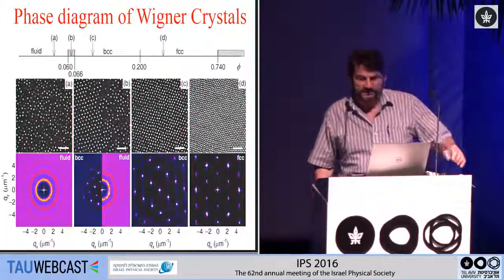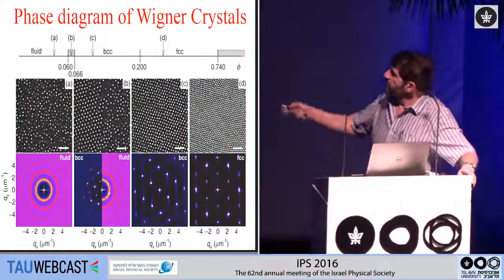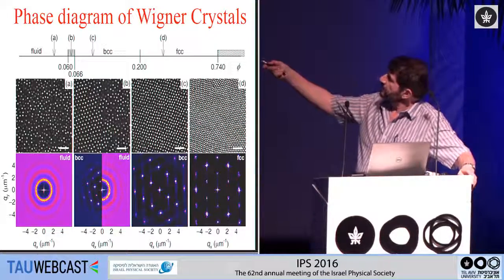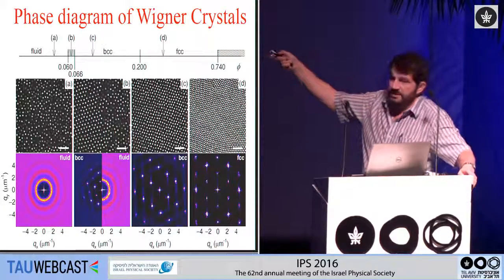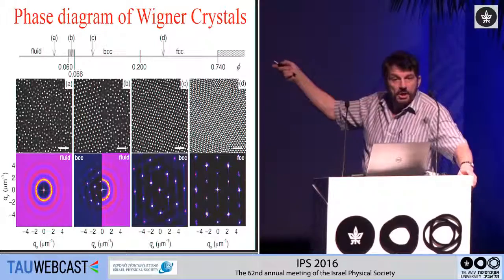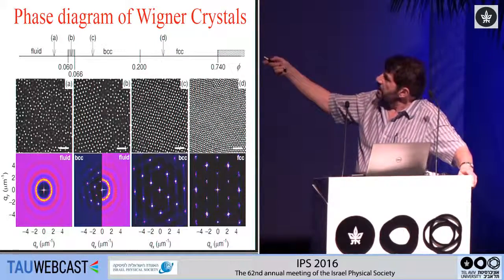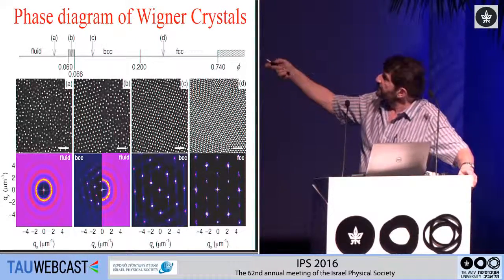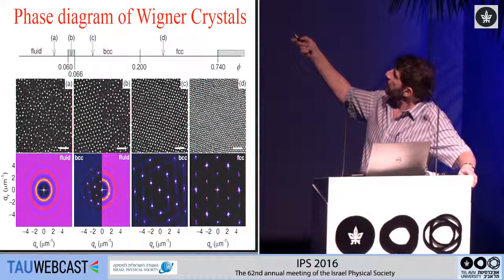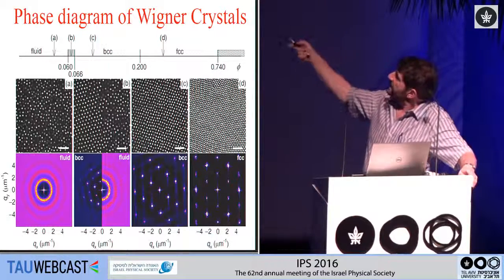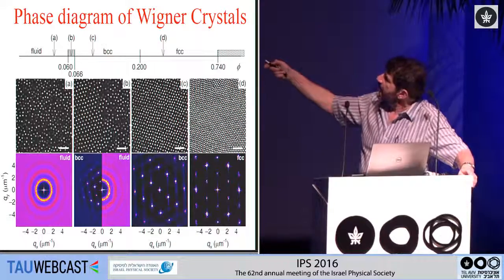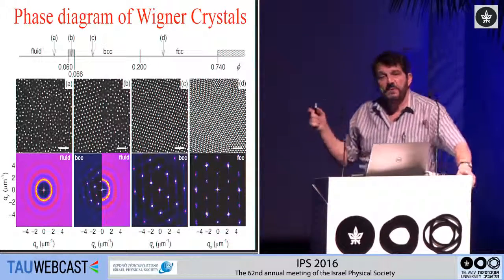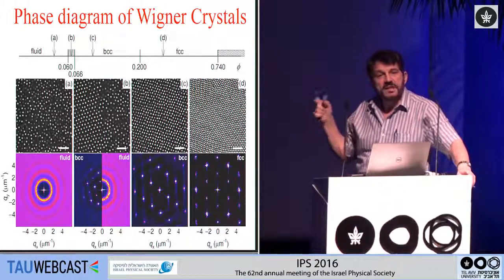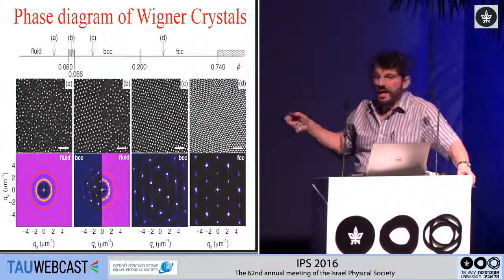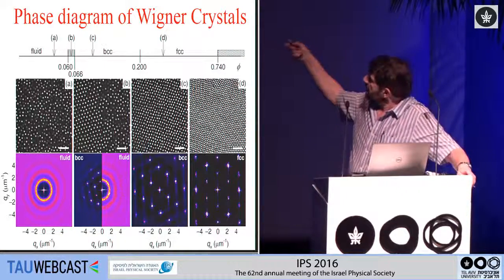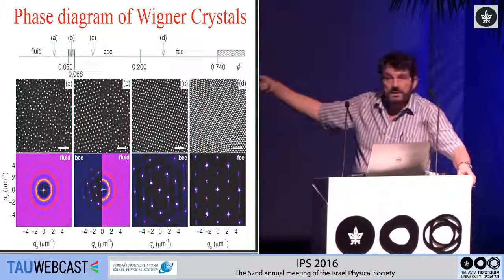And you can look at the phase diagram. These are just snapshots of the images. Of course, the phase diagram now, in this case, is just the concentration. At low concentrations, that's at high temperatures, it's a fluid. At high concentration or low temperatures is FCC. It transitions to BCC. And there is, in fact, a small region of coexistence between the BCC and the liquid. And you can see each of these in real space in these images.